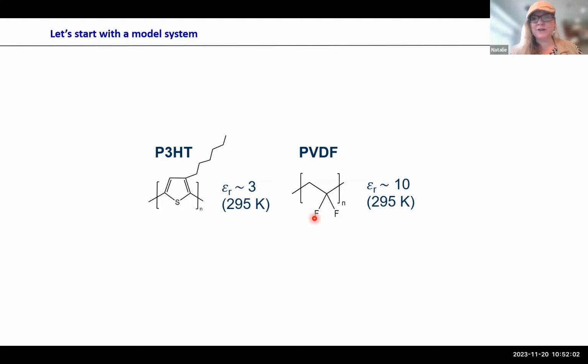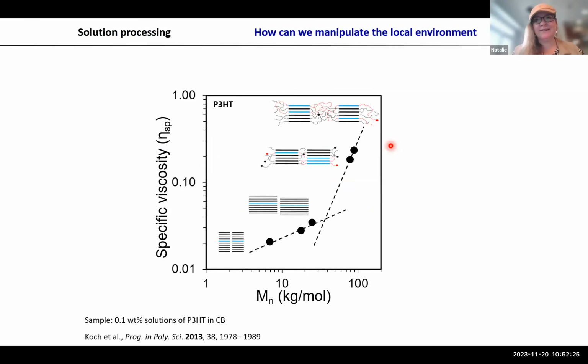But we use PVDF because you have fluorines and here you have hydrogens. So if you have this arrangement of the chain at room temperature, plus minus, you have a much higher dielectric constant. So it mimics, to a certain extent, the polymer environment in an electrolyte, where the electrolyte will increase the dielectric environment.